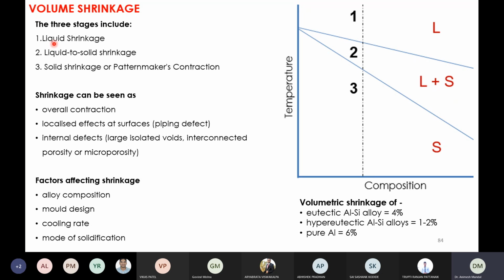Again, as I told, it will depend on the alloying element which is present. For example, let us say a case of a eutectic aluminum silicon alloy. It shows only 4% shrinkage, but if you go for hypereutectic, it shows further lower shrinkage. But pure aluminum, on the other hand, if you can see, shrinks by around 6 to 7 volume percent, where the shrinkage is very, very high. For aluminum, generally, it has a much higher shrinkage as compared to iron or cast iron or those kinds of metals. Okay, so that means your calculations have to be pretty accurate.